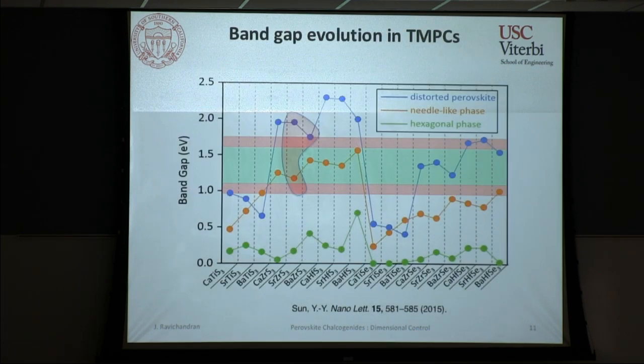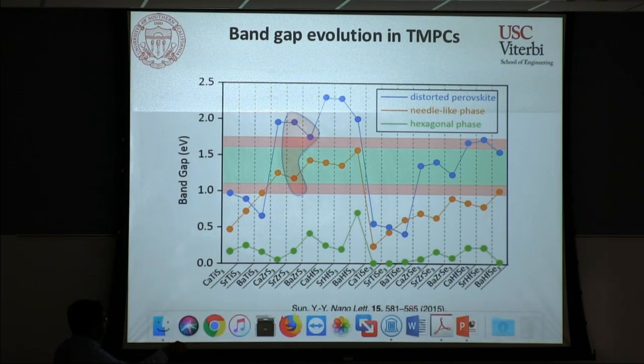Okay, so let's look at this particular graph that I've shown. So this is a prediction of the band gap for these various compounds, assuming it crystallizes in one of these 3 phases. In principle, only one of them is going to be the thermodynamic phase, the ground state of the system, and it's possible that you may have another phase stabilizing close to room temperature. But this is a good starting point that Shengbai Zhang's group at RPI predicted for us to start taking some of these compositions and try to look at them. So the first thing that we started looking at is strontium zirconium sulfide (SrZrS3) and barium zirconium sulfide (BaZrS3), because you can see that the band gap seems to match nicely with the solar optimal value, which means there is a chance of looking at single junction solar cells based on these materials.